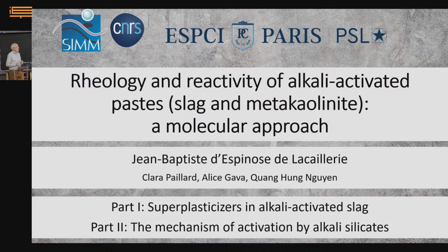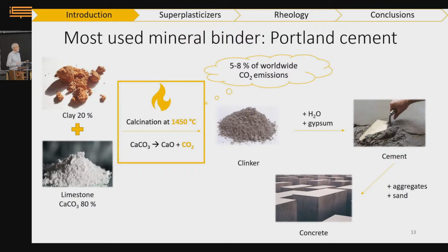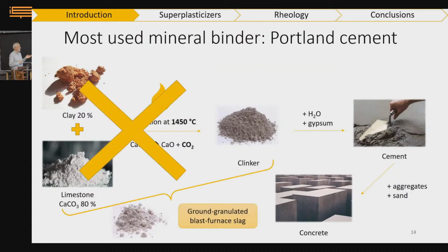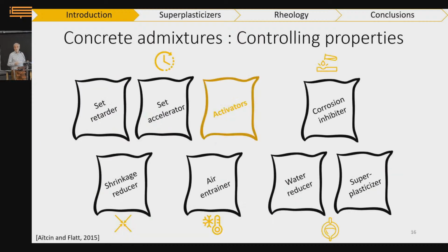So let's start with a general statement. It's very, very fast because you all know that. The beauty of cement is that it's based on calcium chemistry and hence very high reactivity in water, because calcium, as you know, is a highly hydrolyzable cation. But our source of calcium is limestone, and so we have to decarbonate, and this is what we try to avoid, right? So we are substituting cements, or at least clinker, with other sources of silicon and aluminum and eventually calcium, but with less calcium. As a result, we have powders that are less reactive with respect to water. So we have to activate them, right? So to the formulation, we have to add an activator.